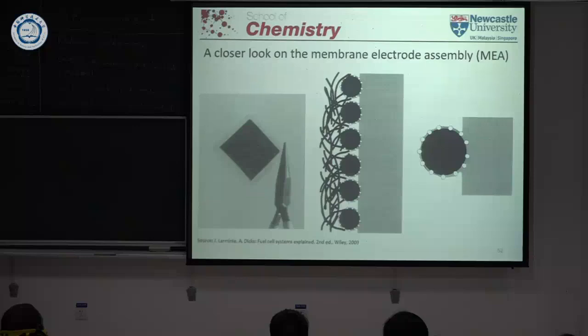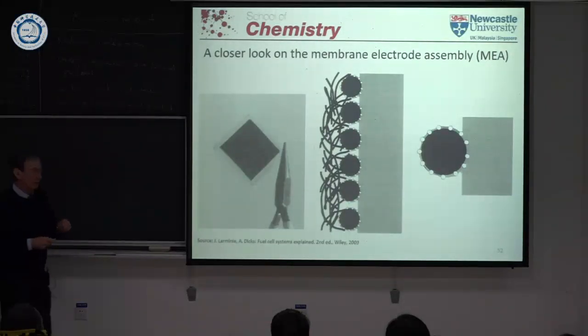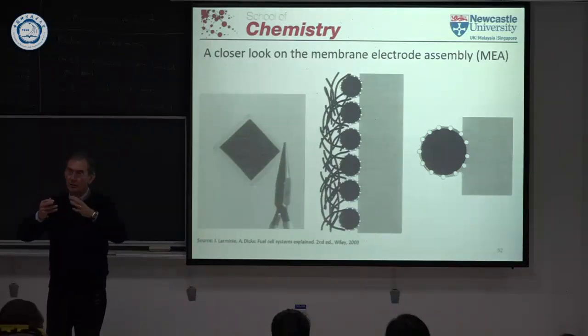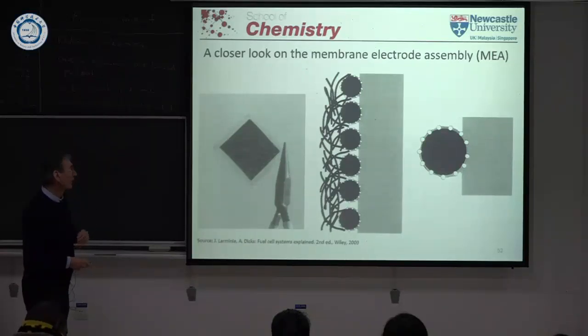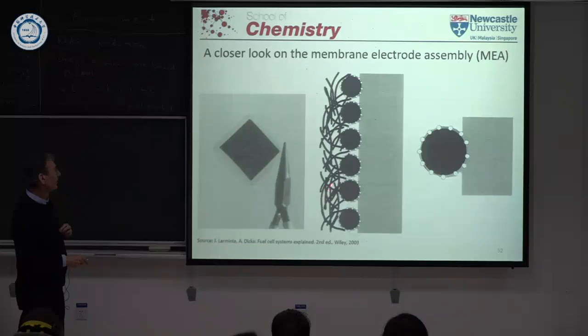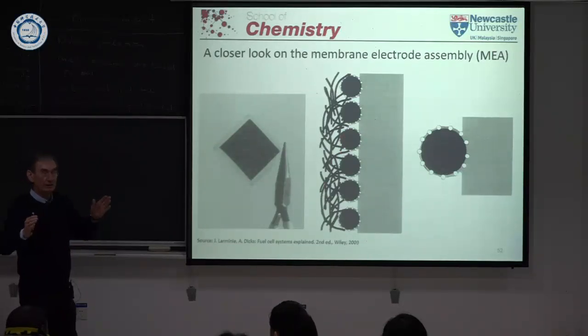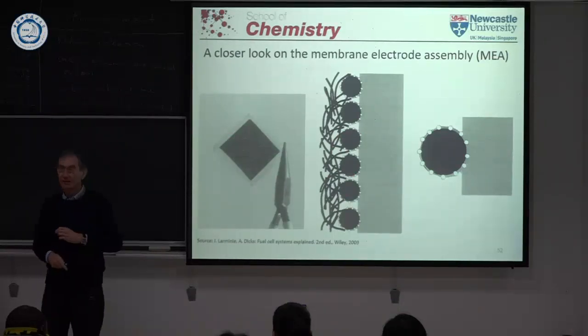Now I think you see, and this picture is actually schematic and shows you now actually how delicate in a way really the construction is. That you have some solid materials as well as these sort of flaky materials, because you need to bring the gas through this layer. This is here the gas diffusion layer, to the catalyst particle, here the carbon with the platinum on it, and you need to be in contact actually with the membrane, which for instance is a problem here. The gas comes in, here's the catalyst particle, but the way to the membrane is rather long, and I have to establish it, so I have to put some Nafion here as well to get the ionic conductivity to the membrane. Otherwise, these particles are inactive.